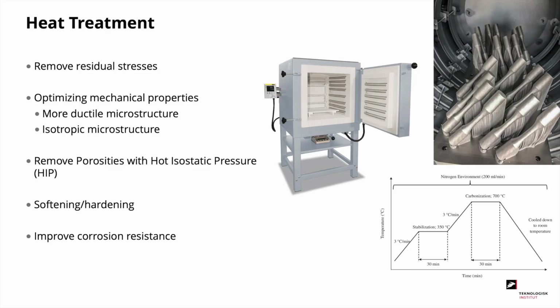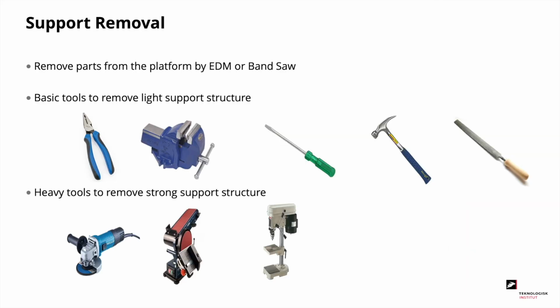One of the more common is to remove porosities with a hot isostatic pressure known as HIP. This is specifically relevant for highly critical parts like aircraft components. It could also be softening or hardening the component. This is relevant for tool applications and tool steel. Finally, it could also be used to improve corrosion resistance, which is relevant for typically stainless steel, but also nickel-based superalloys. Then the support should be removed.